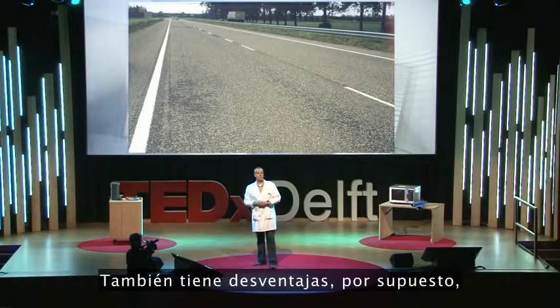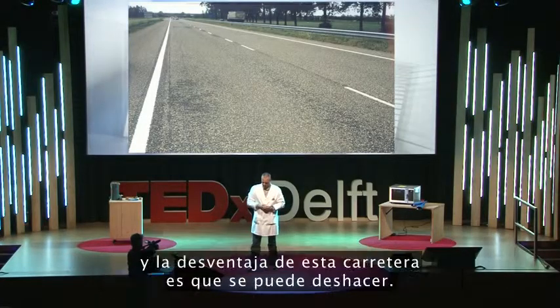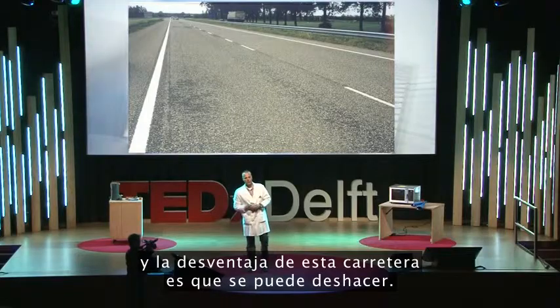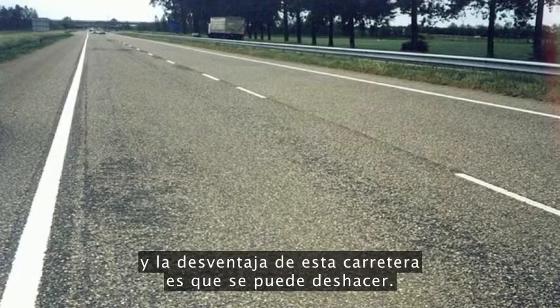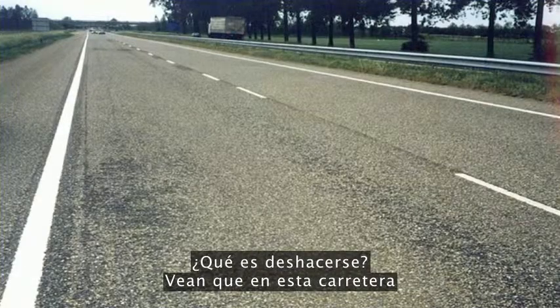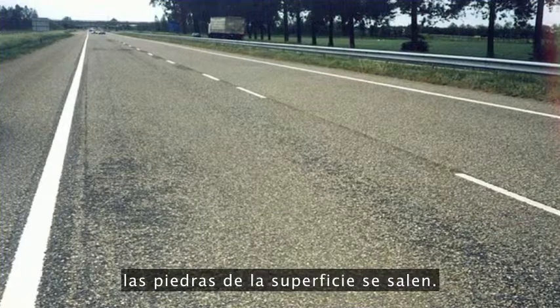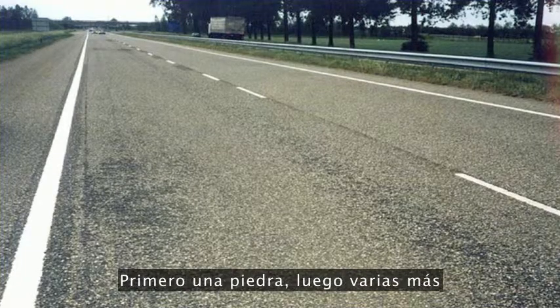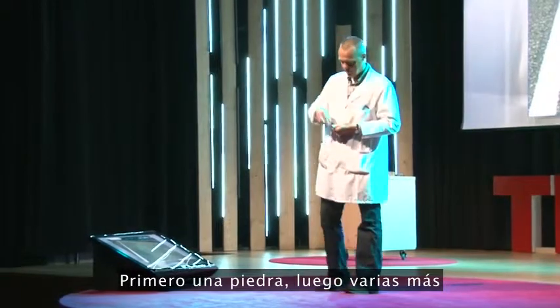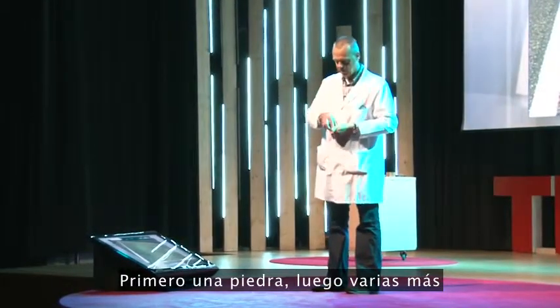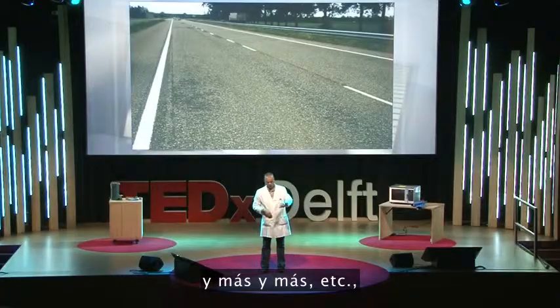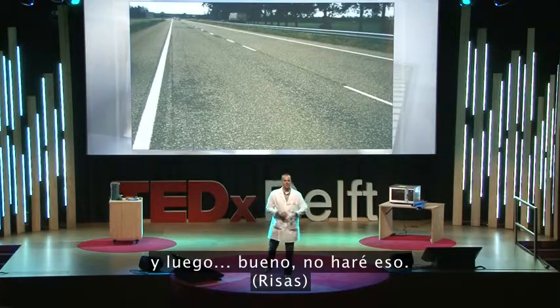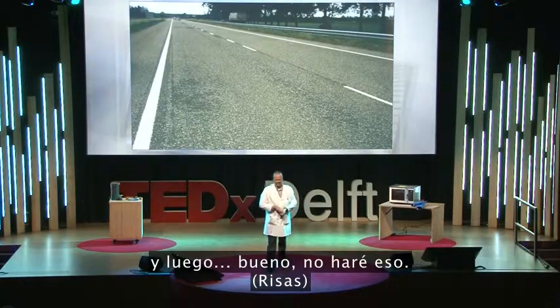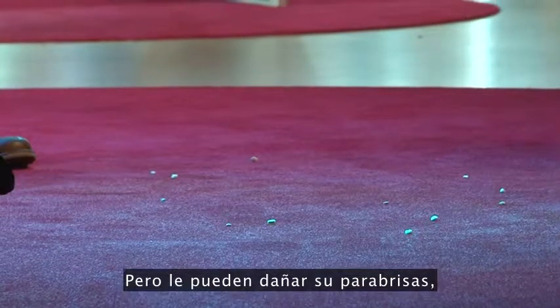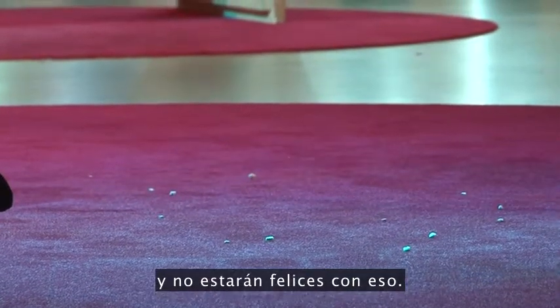It also has disadvantages, of course. And the disadvantage of this road is that raveling can occur. What is raveling? You see that in this road, the stones at the surface come off. First you get one stone, then several more, and more, and more. But they can damage your windshield. So you're not happy with that.